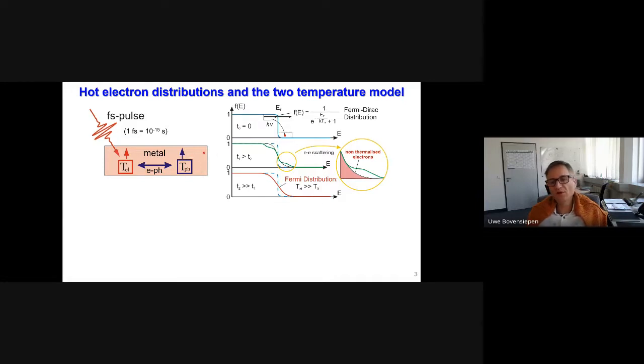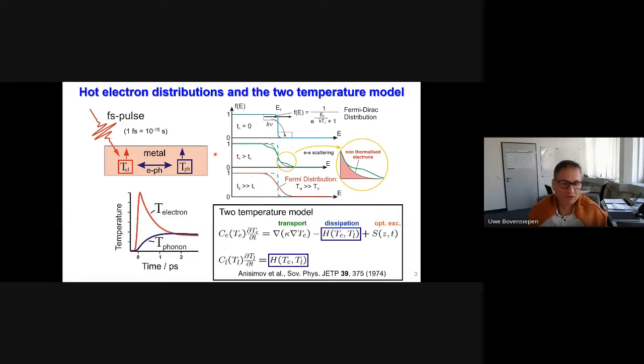So this model suggests this picture that we have the hot electrons in the presence of a cold lattice for a very short moment of time. And this two-temperature model consists out of the description of the electronic system by this electronic temperature and the specific heat, as well as the lattice-specific heat and the lattice temperature. And it's essentially two coupled differential equations. So the first equation for the electrons has here the source term, that is the laser pulse that brings in energy, and the model assumes that all the energy excites the hot electron distribution.